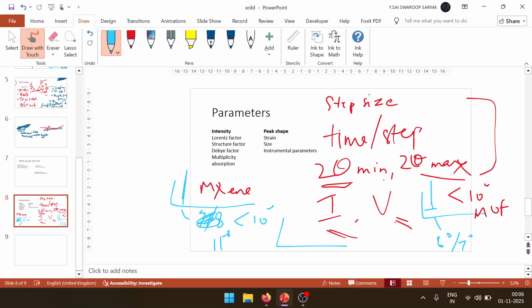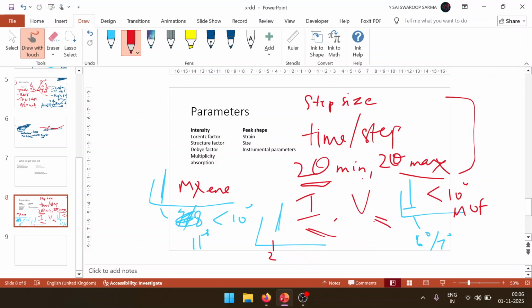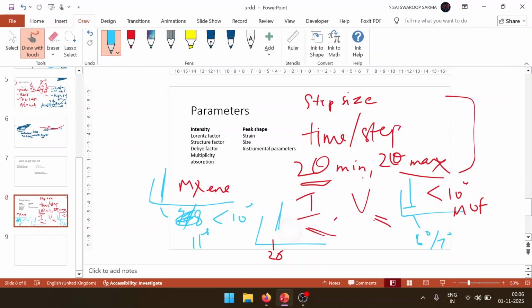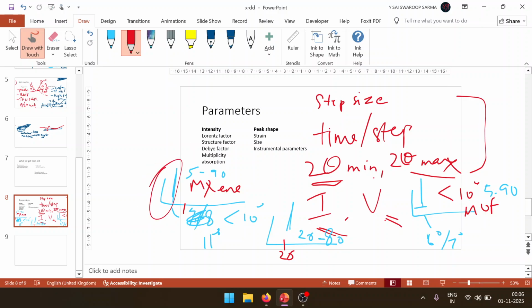In oxides, peaks generally start after 20 or something. So in oxides it's okay if you take 20 to 80, because generally by 80 all the peaks are done. In MXenes you have to go from 5 to let's say 80 or 90. Same in MOFs, 5 to 90 or something. This is what I mean by depending on material. If you take a MXene and start the scan at 20, you won't get this peak, which, as far as I remember, is the characteristic peak showing that MXene has formed from the MAX phase. If you don't see this peak, it means it has not formed. So you may miss some peaks and have to repeat the experiment. Same with MOFs, there is a characteristic peak you need to show that the MOF has actually formed. So just read one paper and you would get an idea of these ranges.